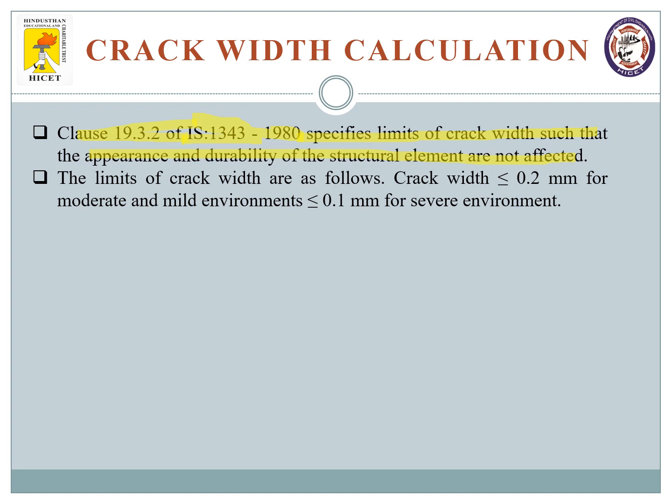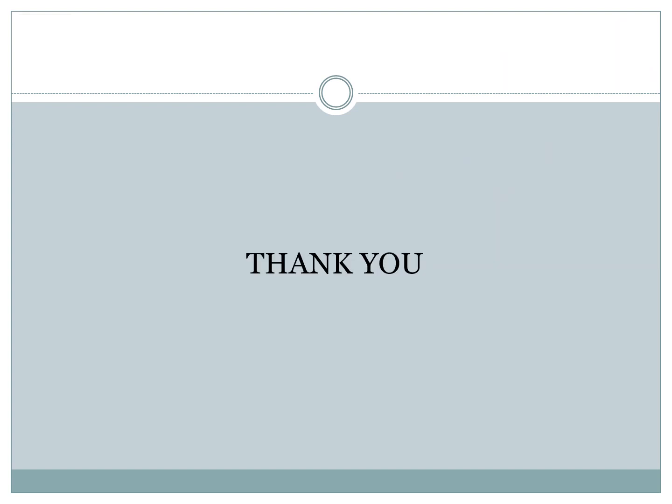If you are going to use a flexural member, what is the crack width that is being allowed? The specification is that crack width should be less than or equal to 0.2 mm for moderate and mild environment and less than or equal to 0.1 mm for severe environment. If the crack width is going beyond this given limit, the section has to be redesigned or if it is a constructed one, it has to be demolished and a new section has to be constructed. Thank you.